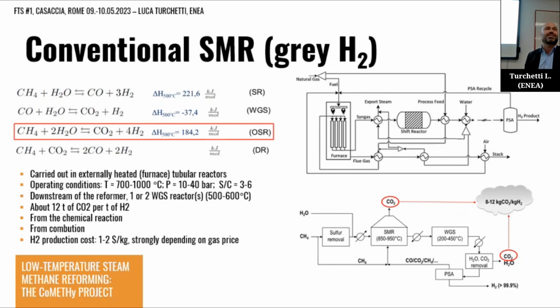So in the end, this process today is associated with big emissions of CO2, both because CO2 is contained in the flue gas of the combustion process we need to produce the process heat to run the process today, and because CO2 is also a product of the reaction we are carrying out to produce hydrogen. This, in the end, leads to the production of up to 8 to 12 kilograms of CO2 per kilogram of hydrogen produced. So it is clear that we cannot continue to rely on this type of process in the future to produce hydrogen if we want hydrogen really to be a clean energy vector, a green energy vector, and a key element for the energy transition.